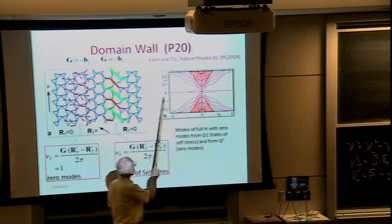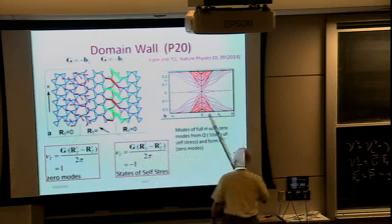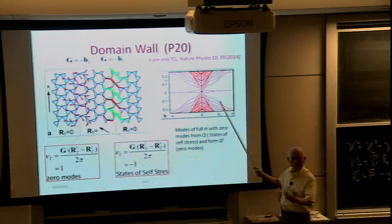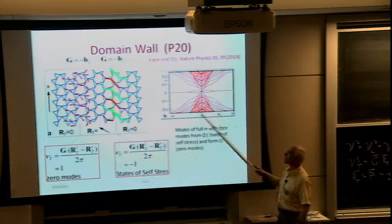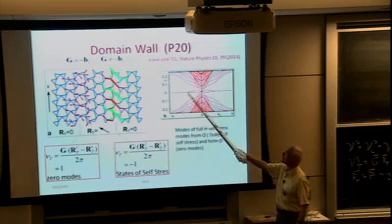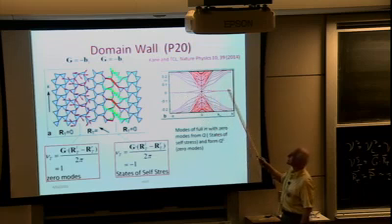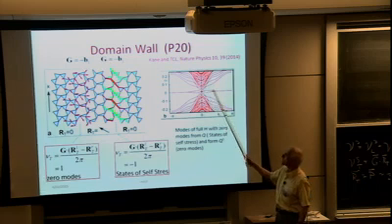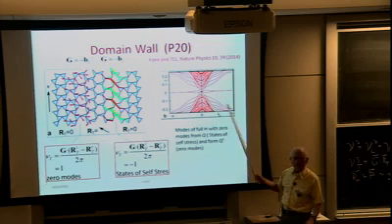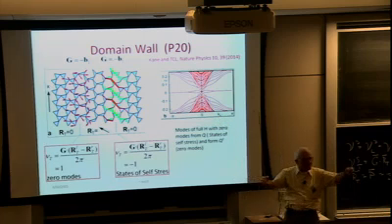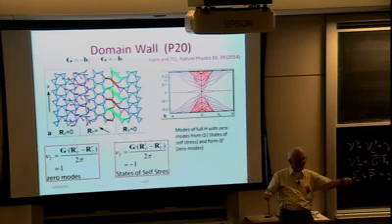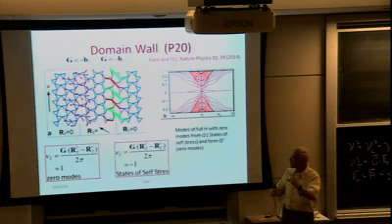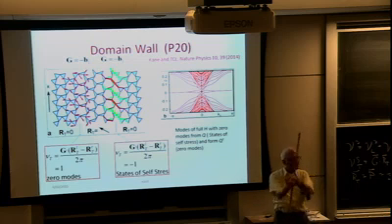So this is a calculation of the full spectrum. This was done for that Hamiltonian that has both the Q and the Q transpose in it. So we have the up and the down ones. And you have these zero modes here that go along. This is the zero mode that we're talking about for every Q, except it comes up and seems to have a finite energy here. And that's because, in this case, we have a system that is finite in size. So when you go to low Q vectors, the penetration depth is much larger, and the wall sees the other side, and you get the energy raised.